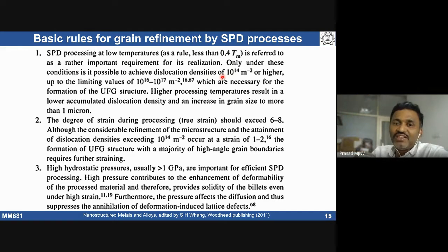That's a different story. We need to induce a very large dislocation density, which is necessary for formation of an ultrafine grain structure. Similarly, we need to induce a very large amount of strain, which should exceed 6 to 8, so that we can get a homogenized microstructure. And hydrostatic: finally we need a microstructure with high angle grain boundaries. If it is low angle boundaries, there are a lot of issues. So we need grains with high angle grain boundary character, and the hydrostatic component is important. Typically, people apply greater than 1 GPa.